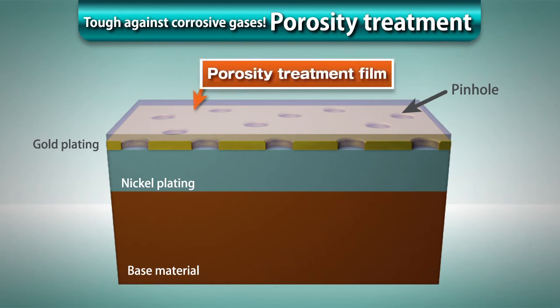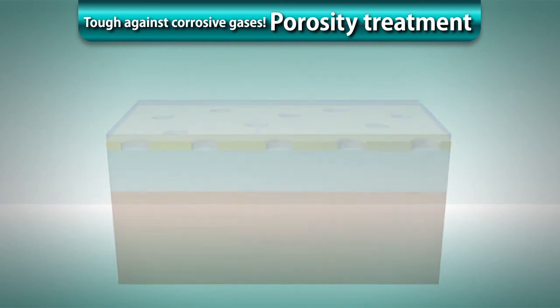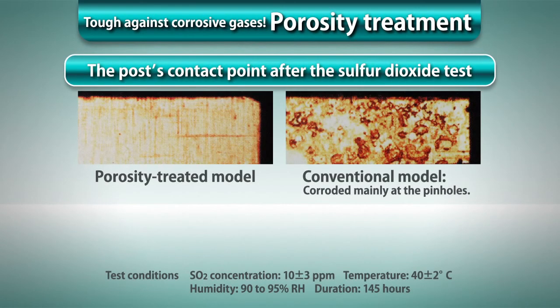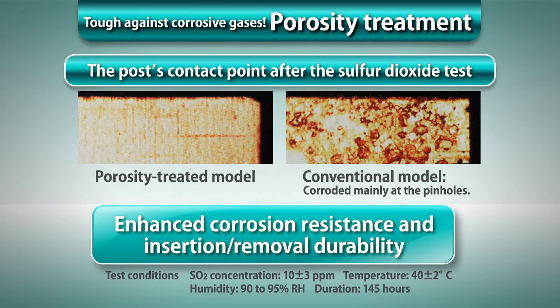Porosity treatment is a technology used to cover the pinhole surfaces with a very thin film. Panasonic has developed its unique porosity treatment material consisting of a synthetic component and lubricating component. The material provides high contact reliability even under adverse environments. This porosity treatment technology enhances the resistance to corrosion by sulfur dioxide and the insertion removal durability, maintaining the high contact reliability.